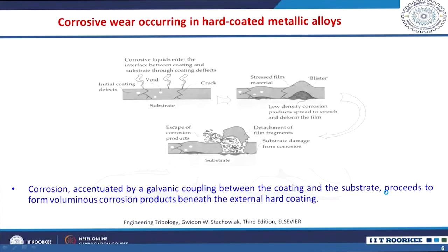The corrosion is accentuated by galvanic coupling between the coating and the substrate, which proceeds to form corrosion products and material removal beneath the external hard coating. If you see corrosive wear occurring in hard coated metallic alloys, initially you have this coating. Corrosive liquids enter the interface between the coating and substrate through several material defects. When the liquid enters, you will have corrosion products. The corrosion products, being less dense, easily spread. Because of this spreading, the coating is stretched and even deformed, and it may even lead to fracture. So the detachment of the coating comes out, and then substrate damage leads to a corrosion increase.